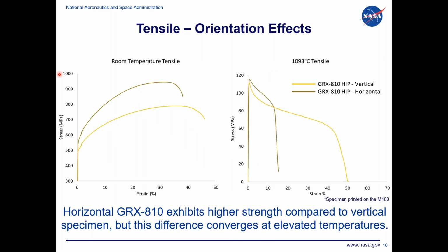We have looked at orientation effects, and I have a lot more data. Our hope is to get a data sheet out very soon. But just some general trends that we saw. For most temperature regimes, the horizontal orientation is usually stronger and just as ductile as the vertical orientation. And that goes all the way up to even 2000 degrees Fahrenheit, 1100 degrees C. Again, both orientations at those really elevated temperatures are still ductile. You do see a little bit of reduction in the ductility in the horizontal orientation versus the vertical one, but it's still a very ductile material even then. And I will say the differences in strengths start to converge as you go up to these very high temperatures.